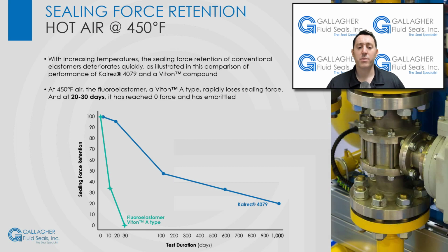With increasing temperatures, the sealing force retention of conventional elastomers deteriorates quickly, as illustrated in this comparison of performance of Kalrez 4079 and a Viton compound. At 450 degrees Fahrenheit air, the fluoroelastomer, a Viton A-type, rapidly loses sealing force, and at 20 to 30 days it has reached zero force and has embrittled. In comparison, Kalrez 4079 has the capability of maintaining sealing force for over 10,000 days.